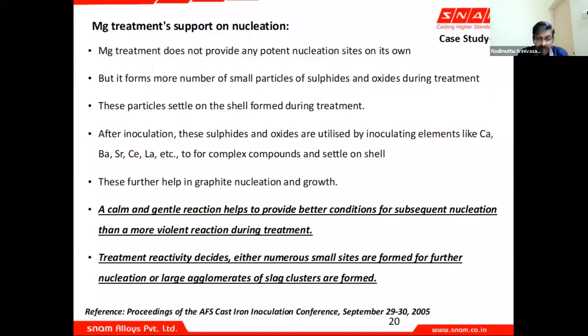The treatment reactivity decides whether numerous small sites are formed for further nucleation or large agglomerates of slag clusters are formed. Generally speaking, we want a good nodule count. A nodule count is a property of whatever I have explained on the nucleation. The way the magnesium and the calcium and the rare earth and then the inoculating element combine, you have a lot of nucleating sites, and they result in a higher nodule count.